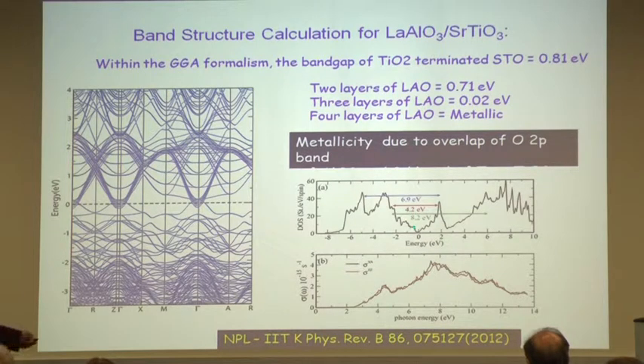And if you look at the transitions from the valence band to the conduction band, most of these transitions lie in the UV range. And that's why the system is sensitive to UV light. So we have calculated the optical conductivity, and you can see that it starts showing up above about 2.2, 2.3 electron volt energy.